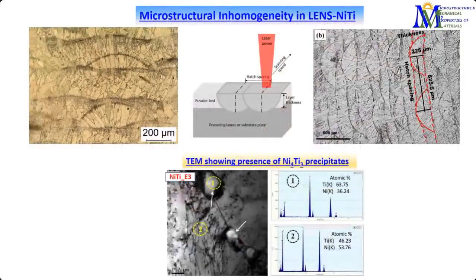This is how the hatch structures are formed, and we've characterized the hatch spacing and layer thickness, which vary distinctly for the three different energy densities used. Most interestingly, the one prepared with the highest energy density has shown some precipitates forming. These are Ni-rich precipitates, and this certainly will have a huge role to play in the properties of the material. We'll look into that shortly.